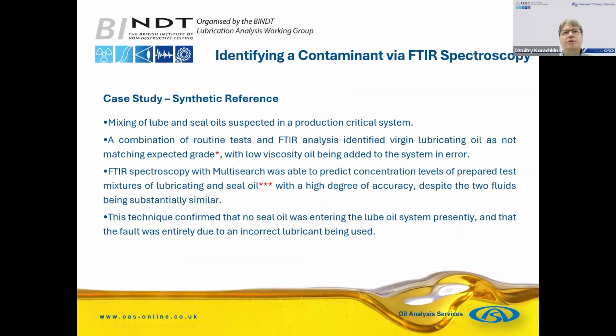Another case study, we had suspicion of seal oil getting into the lubricating oil. We performed infrared analysis, some other tests, and they have provided us a sample of virgin oil. And we found that the virgin oil sample that they have provided us was not matching the expected grade. And that's why the viscosity was different. So we used infrared spectroscopy as well to check the concentration levels of prepared test mixtures of lubricating and seal oil. We were able to predict it with a high degree of accuracy, and we were able to confirm that actually there was no seal oil in the lube oil, and that the fault was entirely due to an incorrect lubricant being used.